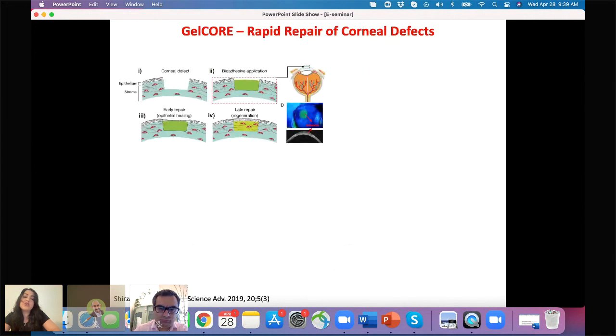So here are some initial data that we started in our academic lab based on the use of a gelatin-based bioadhesive. We call it GelCORE, gel for cornea repair. We optimized the formulation of the GelCORE for rapid repair of corneal stromal defect. Basically, GelCORE can be injected inside the corneal defect and photopolymerized. Once the hydrogel is solidified, epithelial cells can grow on the surface of the hydrogel, and the hydrogel can degrade over time, and we observe tissue regeneration over time.